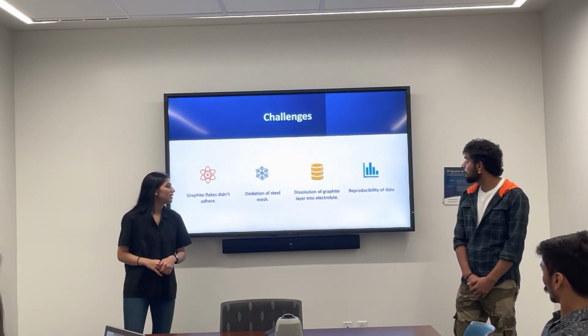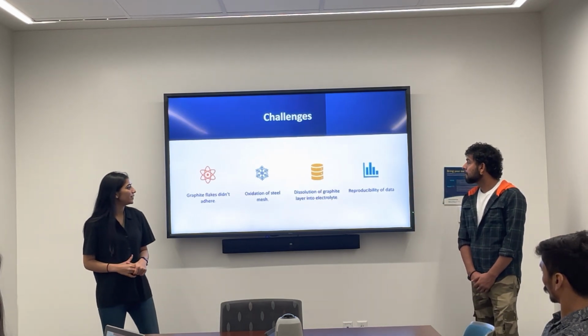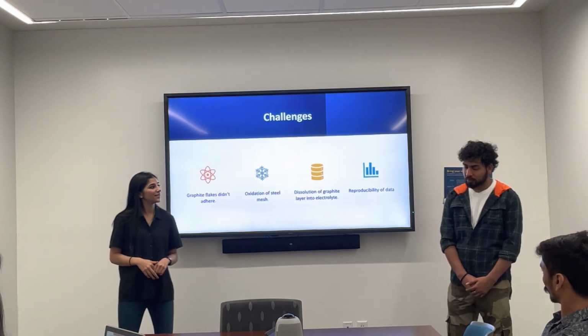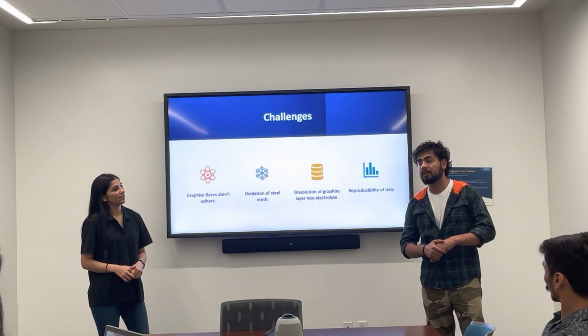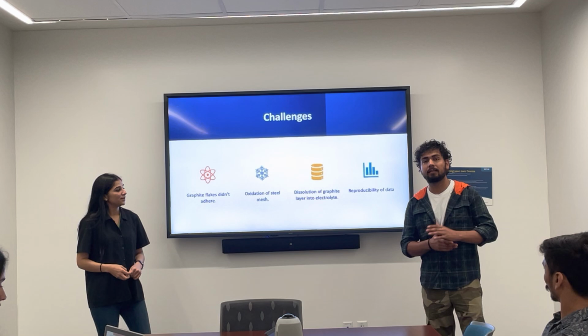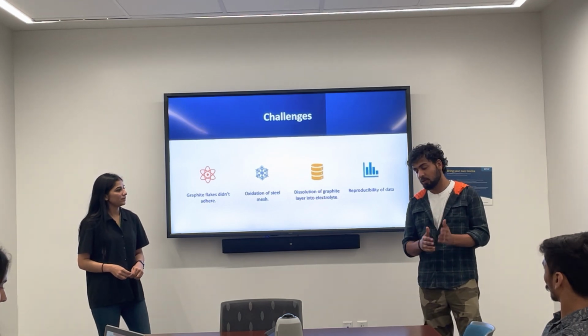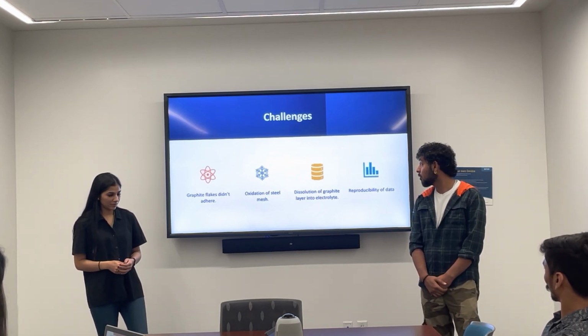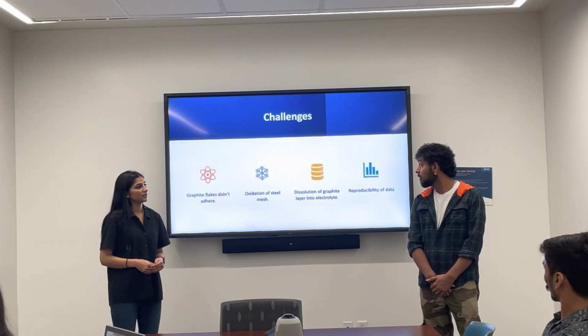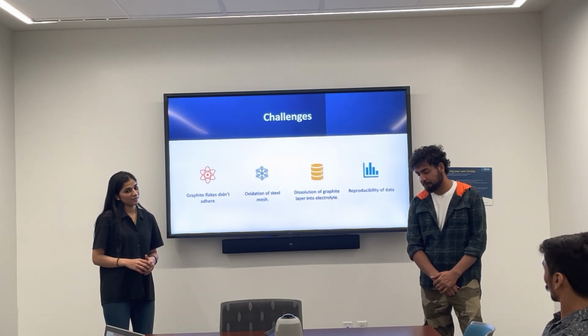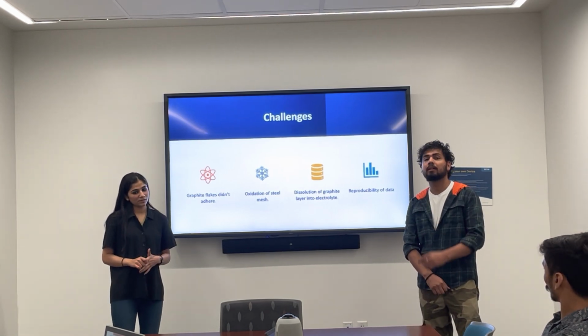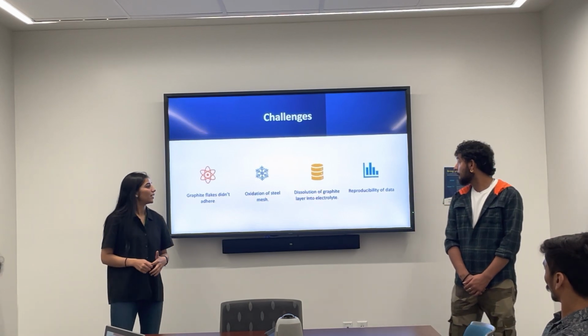And the most difficult one was the dissolution of the graphite layer into the electrolyte. What happened during the reaction is that the graphite slurry went into the electrolyte and goes to the anode, so that corrodes the anode faster. To overcome this, we removed that step and we used a graphite rod. Next slide.